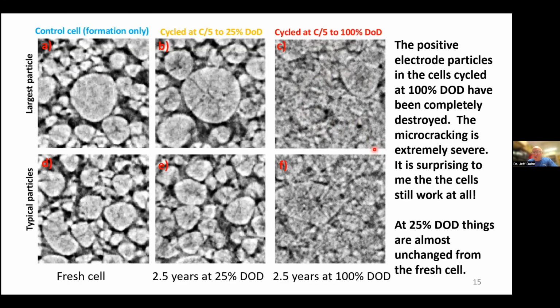And to be honest with you, it's surprising to me that the cells still work at all when the positive electrode is in this condition, but they do. They were still delivering about 80%, or maybe it was 75% of their original capacity. But you can see the advantage of doing low depth of discharge cycling very clearly in this image. It's quite spectacular.